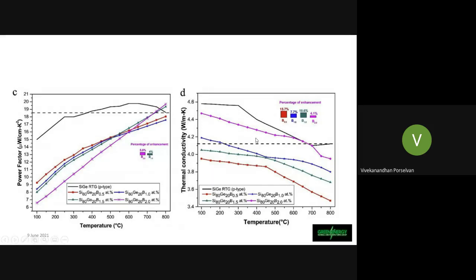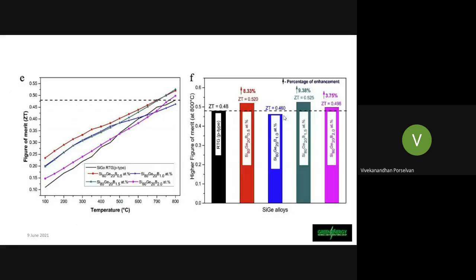And if you look at the thermal conductivity, the synthesized alloy is showcasing a drastic reduction in the thermal conductivity. It is due to the ultrafine scale along with the introduction of the boundary effects by the boron. So it is quantified that the reduction in the thermal conductivity is higher, around 15.7 percent, than the RTG alloy. So this is an increment in the figure of merit of the silicon germanium alloy, showcasing 8.33% as compared to the conventional alloy which is in use.